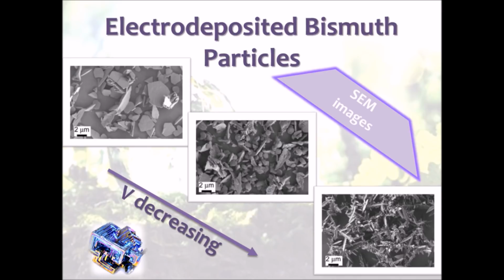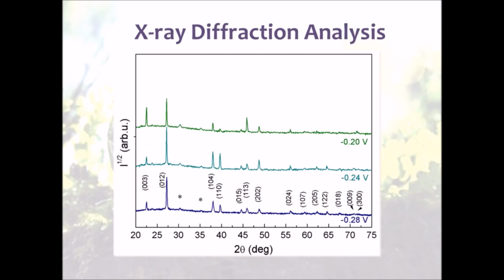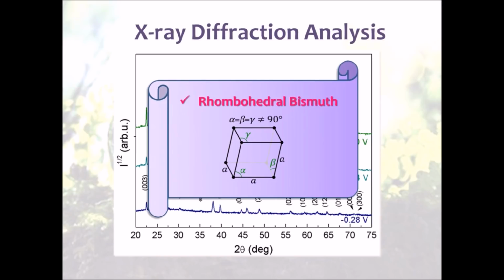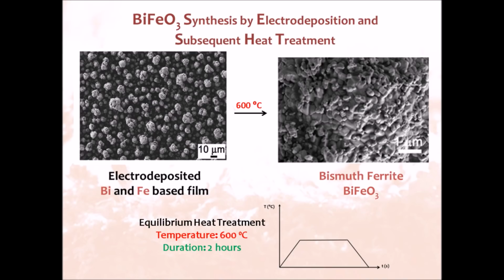When checked out by scanning electron microscope, we see that electrodeposited bismuth particles show a morphological variation from hexagons to dendrites as the applied potential is decreased. When X-ray diffraction is carried out for the structures grown at a series of applied potential values, it's confirmed that rhombohedral bismuth is obtained. For several cases, the crystal structure required is obtained by manipulating electrodeposition parameters. However, there are cases in which post-treatment must be used in order to induce crystallization. For instance, 2 hours of equilibrium heat treatment at 600 degrees Celsius must be applied in order to obtain bismuth ferrite crystals with prism morphology.